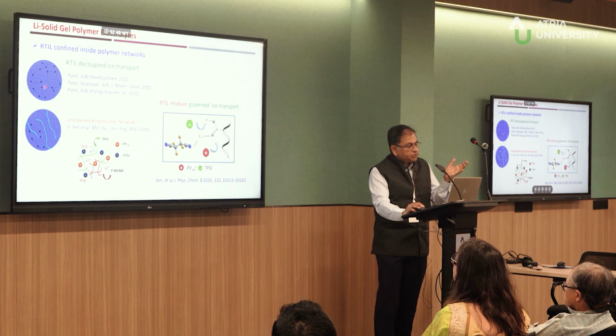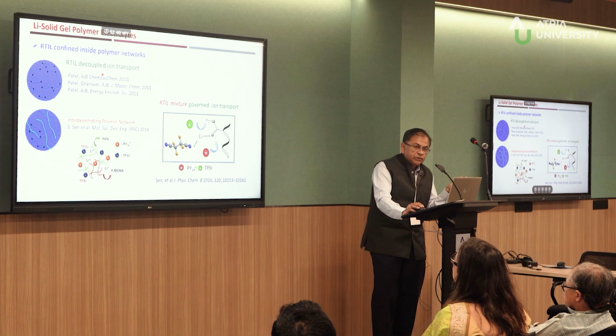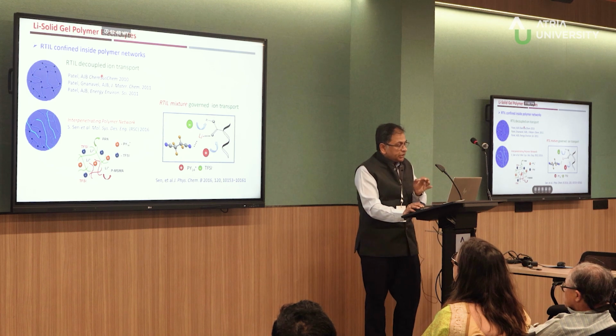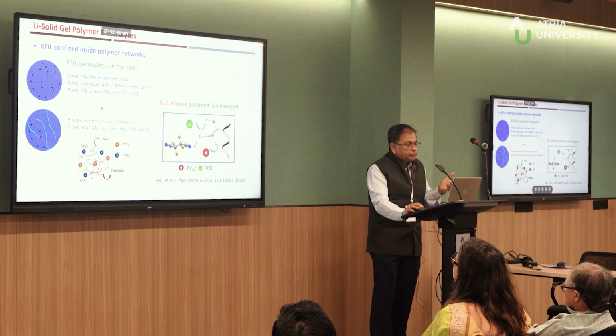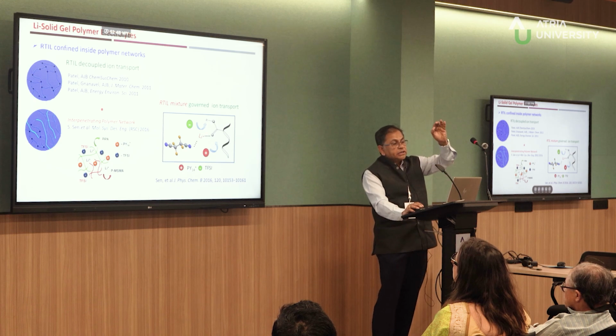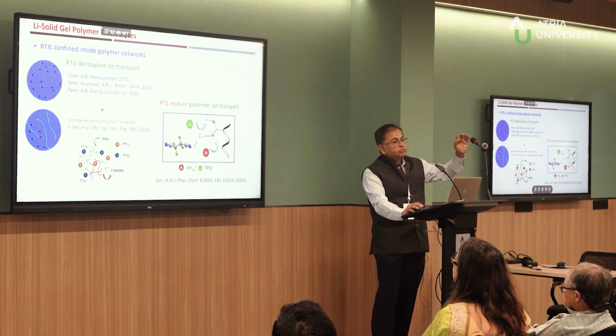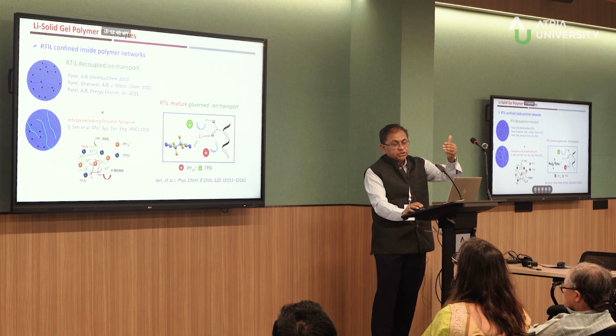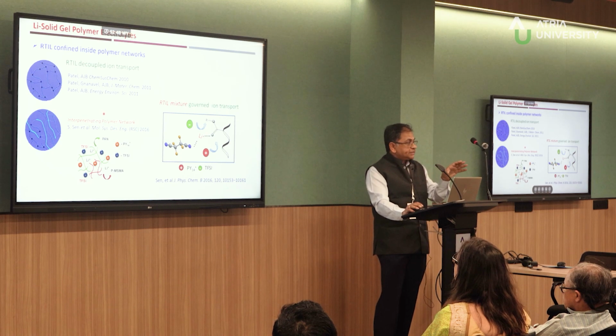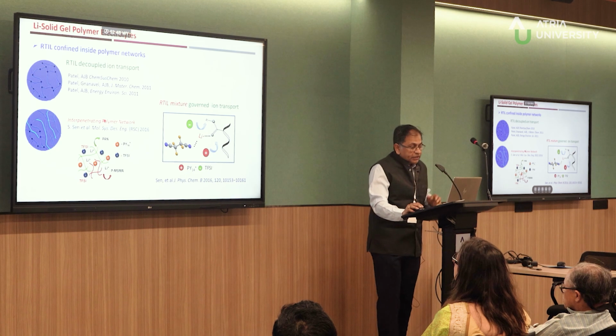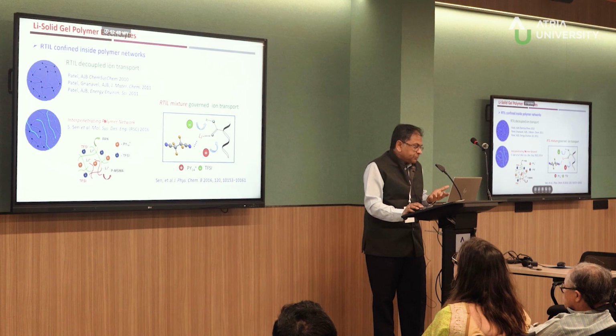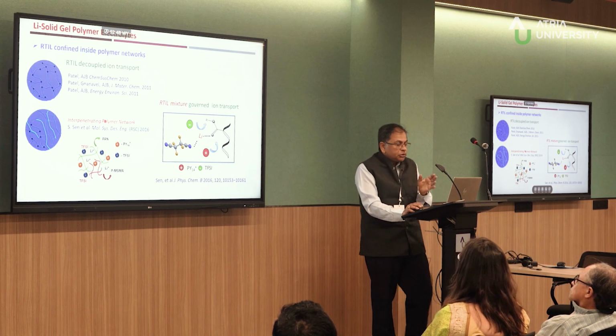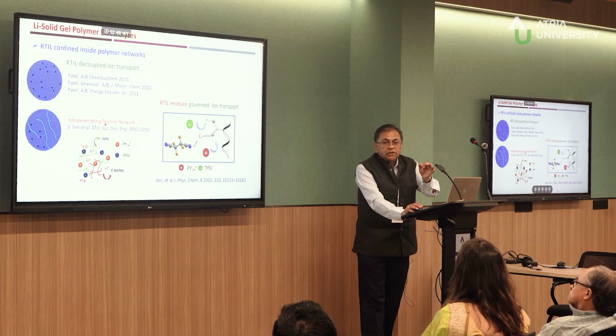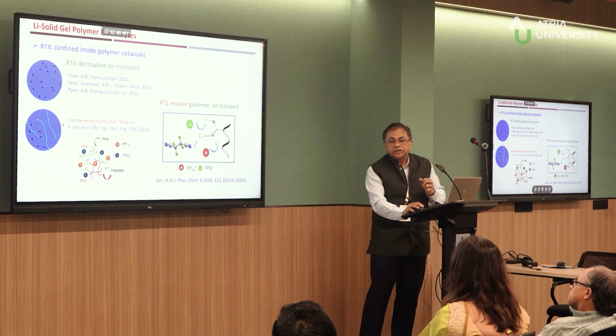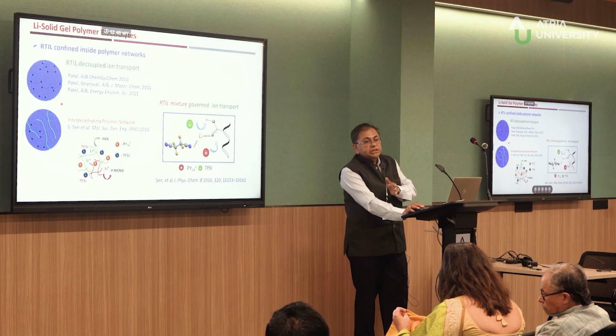You actually make a cross-linked system, and your liquid is trapped inside. It could be a molecular solvent liquid, or it could be a room temperature ionic liquid. In the earlier designs, what we were focusing on was how the ion, let's say lithium or sodium, can be decoupled from the room temperature ionic liquid. Okay, so that the dynamics of the ion in the system is still controlled by the polymer. Okay, so of course you can run batteries with these, but the problem comes when you actually want to scale it up. We are academic labs. We're always at the level of 2032 coin cells, but I think over the last 5-6 years, we are actually scaling up to power cells of various sizes.